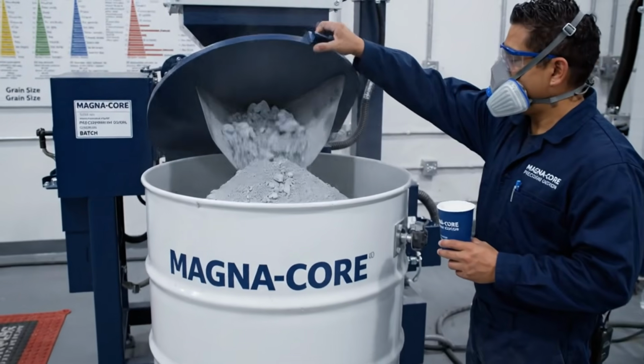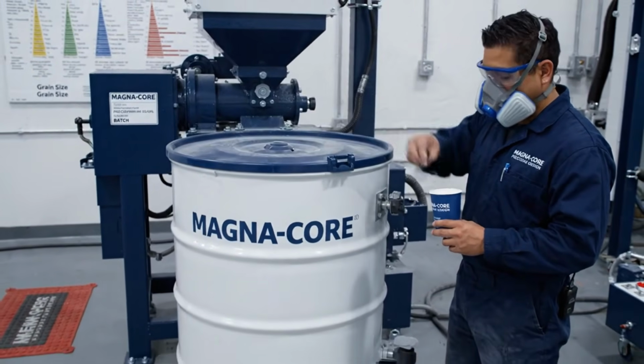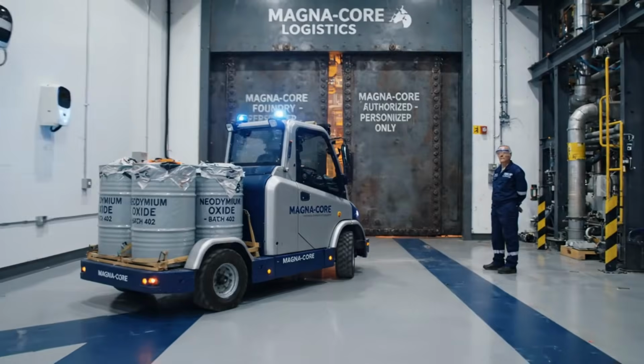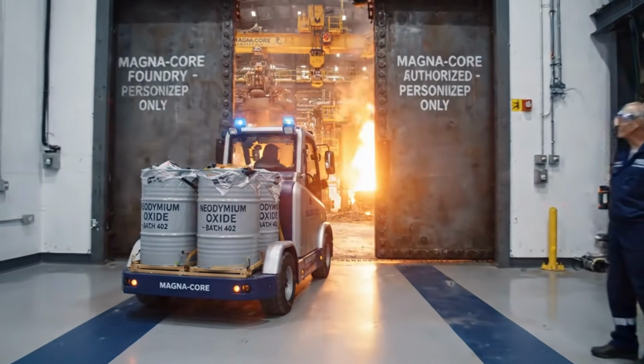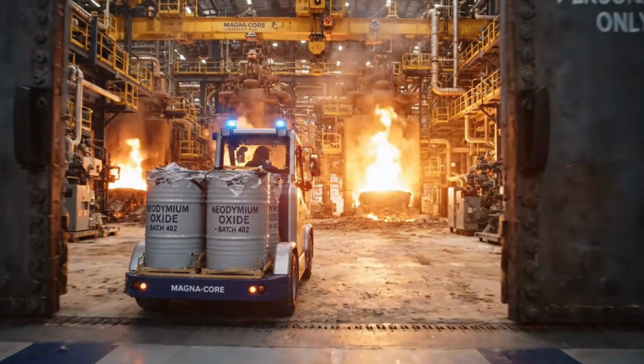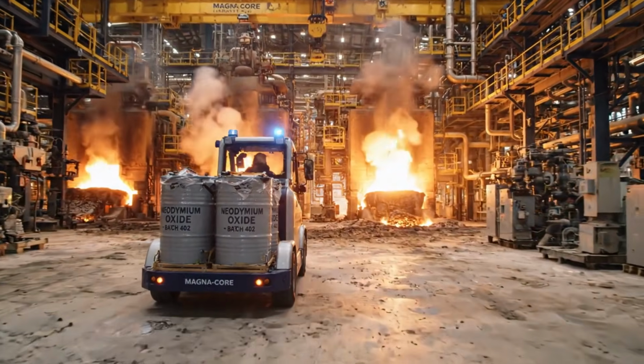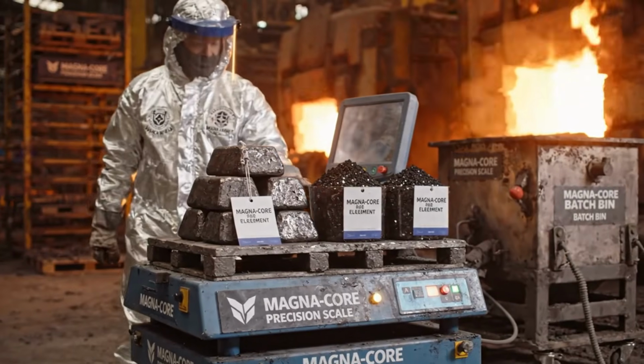The solid strips are placed in a hydrogen atmosphere, which causes the material to crumble into small flakes. High-pressure nitrogen jets pulverize the flakes into an ultra-fine powder with particles only a few microns wide. Because the powder is highly reactive, it must be stored in an inert nitrogen environment at all times.